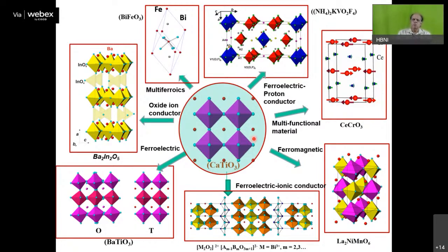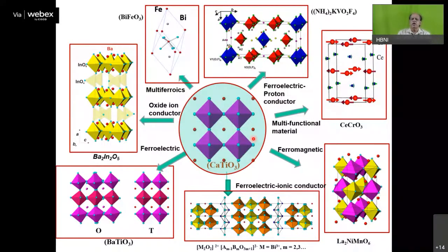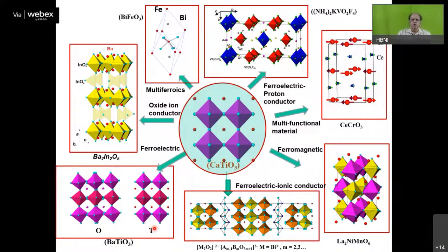So in turn, you have to move away from symmetry and you have to move away from high stability. So you have to go for low symmetry and low stability materials to make different types of functional materials. Replace calcium by barium, you introduce some distortion in octahedra at B side and you convert a useless material into an excellent ferroelectric material. You can create some oxygen vacancies by chemical jugglery, and at certain concentration, oxygen vacancies undergo ordering and you get a related structure which is called brownmillerite, Ba2In2O5. This compound is used as an oxide ion conductor.